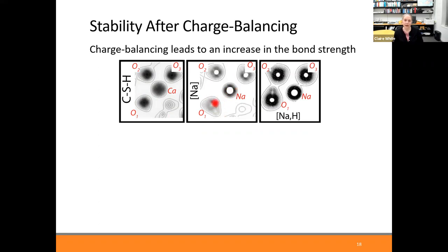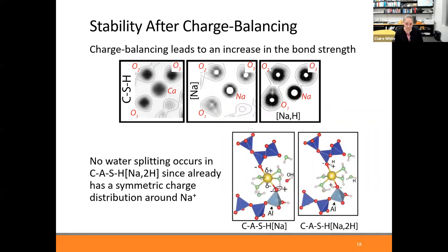And also they're not as black, which is giving you an indication that there's weaker bonding happening between these atoms. However, when there's a hydrogen in the system as well, you can see that the bonding strength has increased. So this is one of the ways that we've been able to get a sense of what impact hydrogen is having on the system through this charge balancing mechanism.